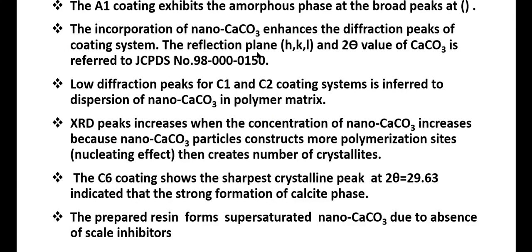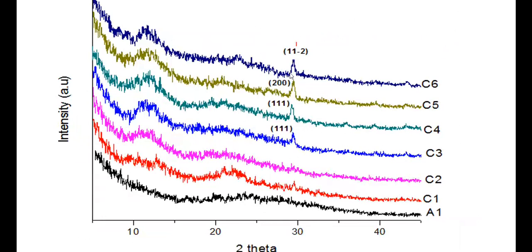Now over here, the low diffraction peak at the C1 and C2 coating systems is inferred due to the dispersion of nanocalcium carbonate in the polymer matrix. The XRD peak increases when the concentration of nanocalcium carbonate increases because nanocalcium carbonate particles construct more polymerization sites, which then create a number of crystallites. So the C6 coating shows the sharpest crystalline peak at a 2 theta angle of 29.63, indicating a strong formation of calcite phase, and the prepared resins are supersaturated with nanocalcium carbonate due to the absence of scale inhibitors. That is over here, C6. You can see the sharp peaks due to the formation of nanocalcite of calcium carbonate.